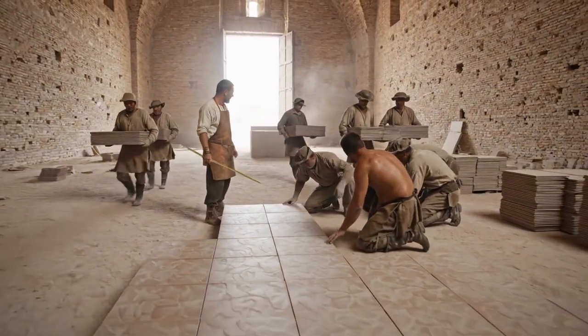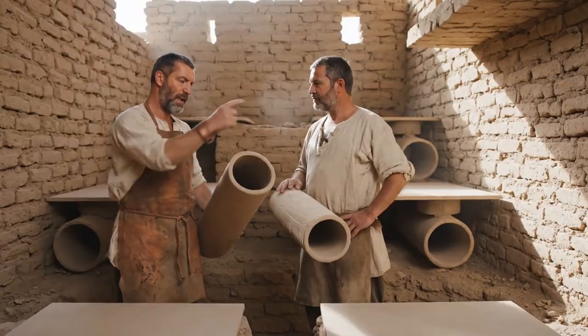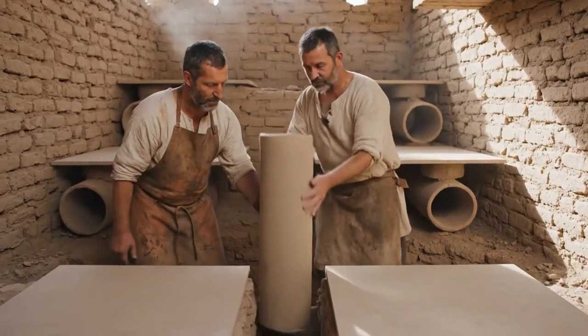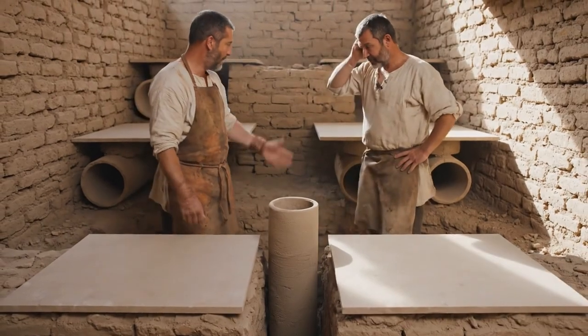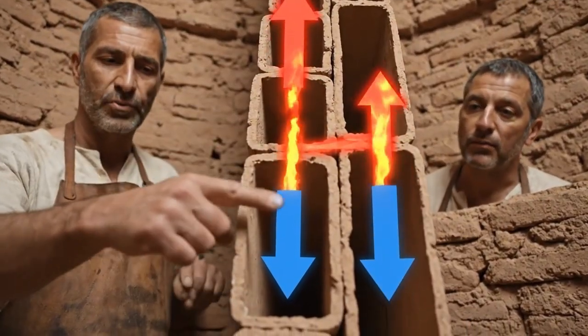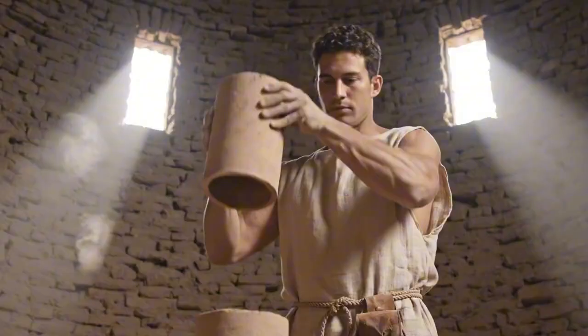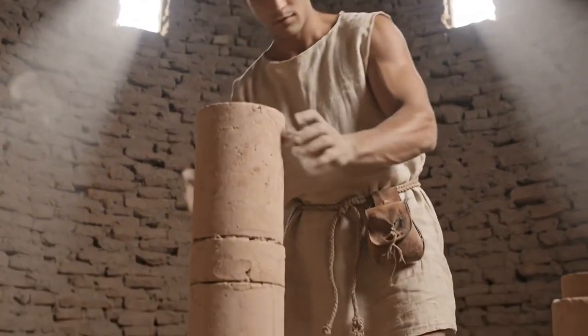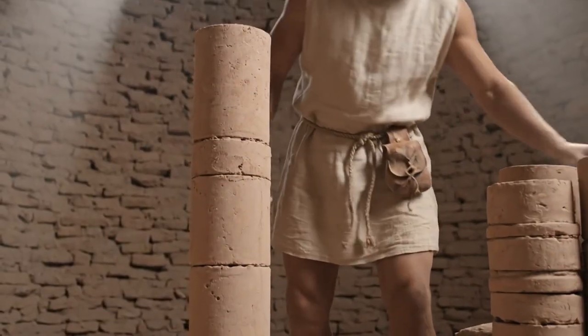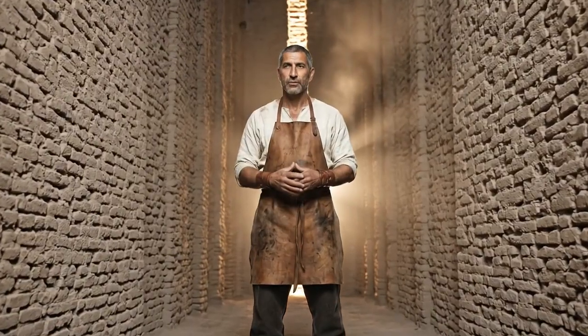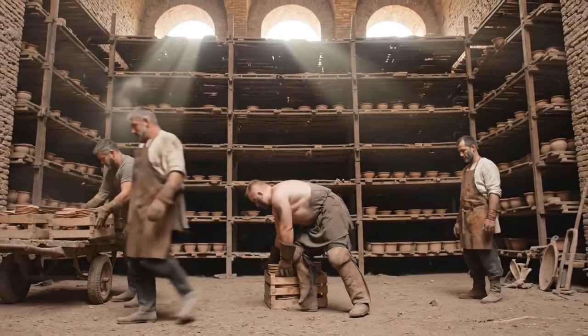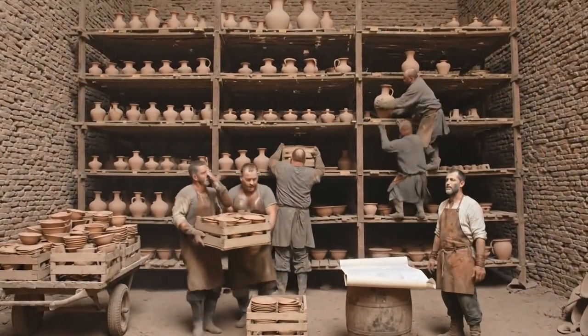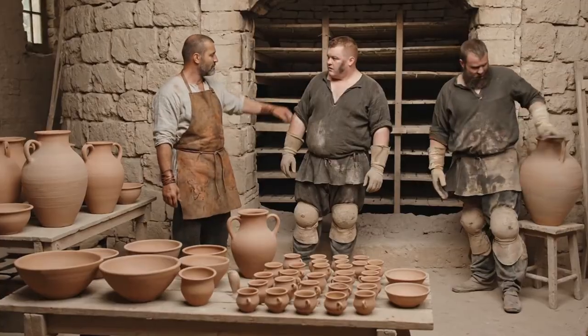Inside this chamber, workers construct up to 9 temporary stories before each firing. The floors of each story are laid from flat ceramic tiles, and the vertical supports that hold them apart are tubuli, hollow clay pipes, or tubes that serve a dual purpose. They bear the structural load of thousands of stacked vessels above, and they act as heat conduits, channeling hot gases from the combustion chamber below upward through every level of the kiln. Without these tubuli, the uppermost floors would receive only a fraction of the heat reaching the lowest, and the firing would be catastrophically uneven.